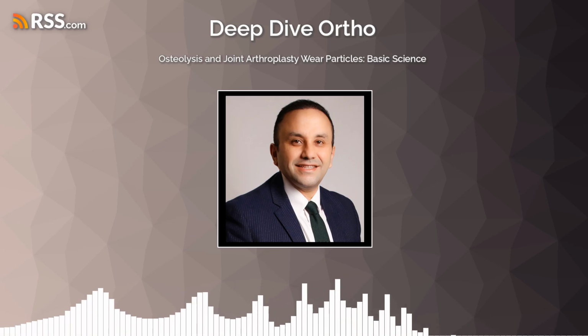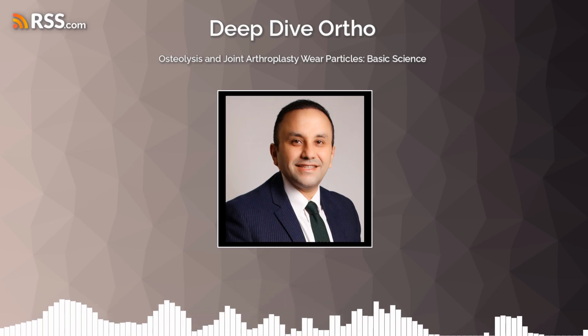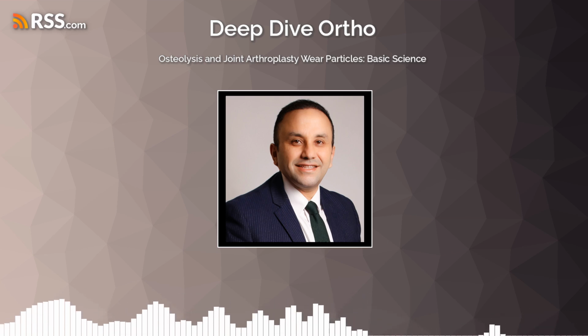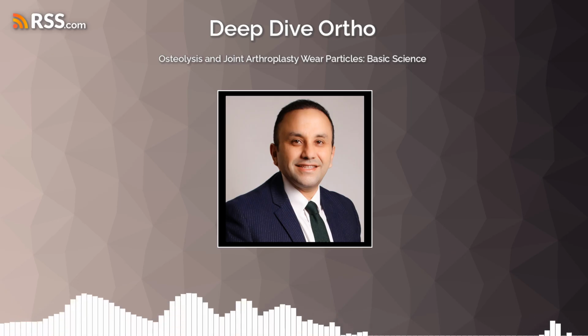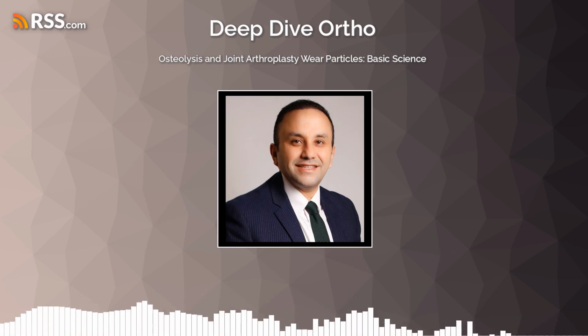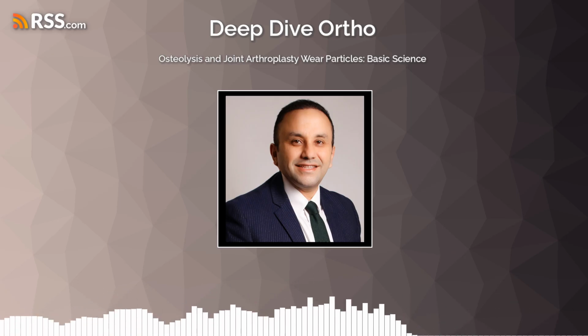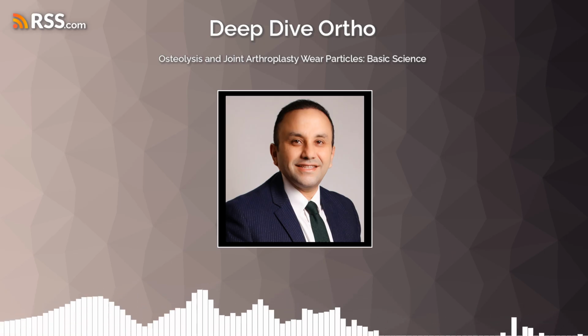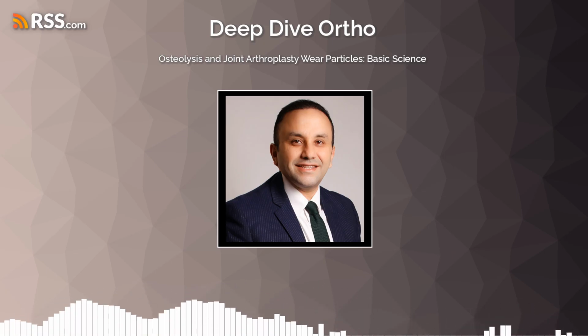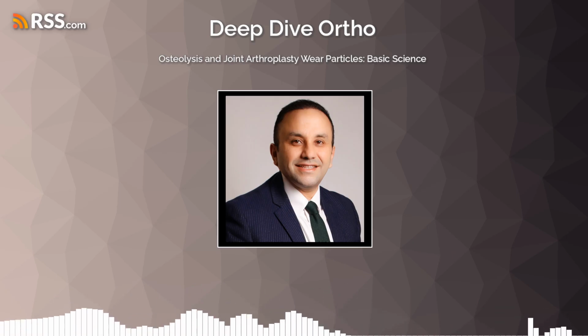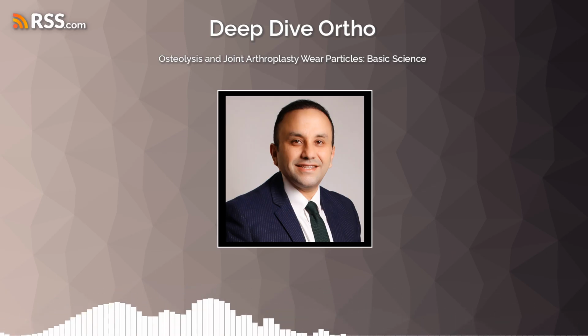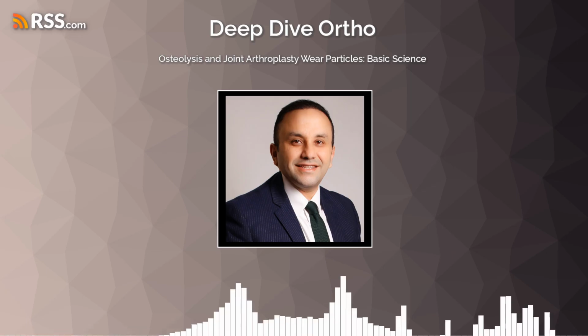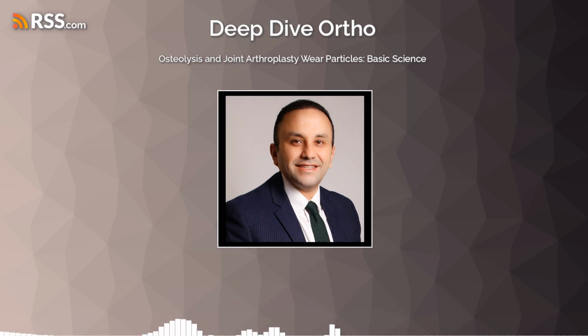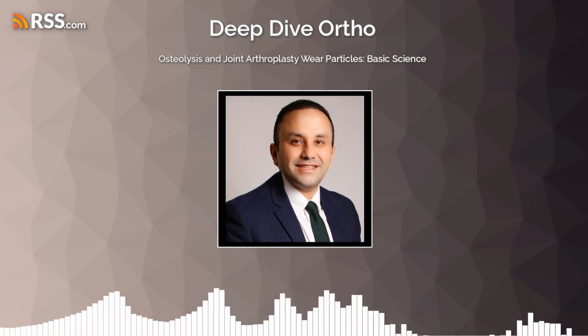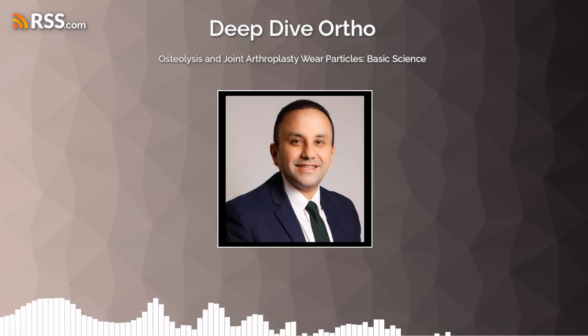They're essentially sterile, fluid-filled, or solid masses that can develop around the implant in response to the metal debris and this intense lymphocytic infiltration. They can be quite destructive locally. Furthermore, metal-on-metal serum ion levels, which we can measure in the blood as an indicator of wear, are found to be greater when the cup abduction angle exceeds 55 degrees and with smaller component sizes. So surgical technique and implant choice really matter there. Critically important, yes. They can exacerbate the problem significantly.